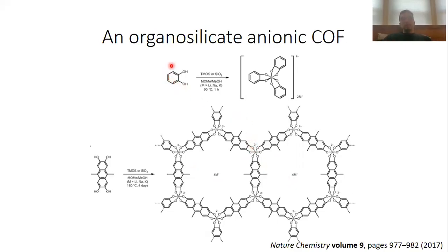So when you react catechol with tetramethoxysilane or simply SiO2, then you're forming this anion here, in which you have silicon octahedrally coordinated by these oxygen atoms, which belong to these 3 different catechol units, and that reaction can proceed base catalyzed in an organic solvent like methanol, so for example, using lithium methoxide dissolved in methanol.